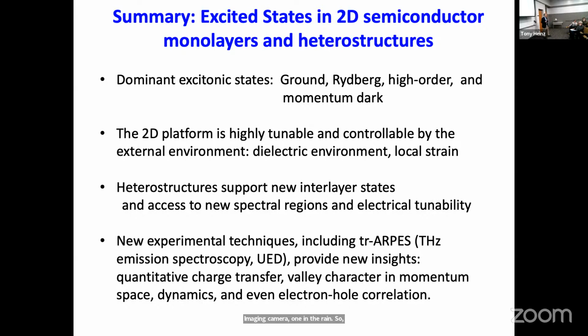Even though the biexcitons are very clear experimentally, not that much has been done with them actually. When we first looked at this, we created them by having a fairly high density of excitons with the pulse. It turns out in these encapsulated samples, where all the features are much easier to see and non-radiative rates are lower, you see them very easily with CW excitation. So they're pretty prominent, but people have not really gone the next step. So maybe you have some good ideas.